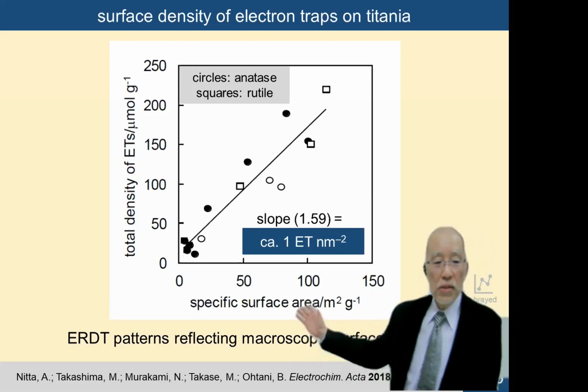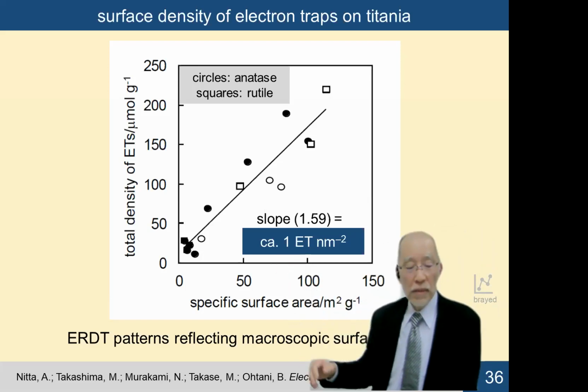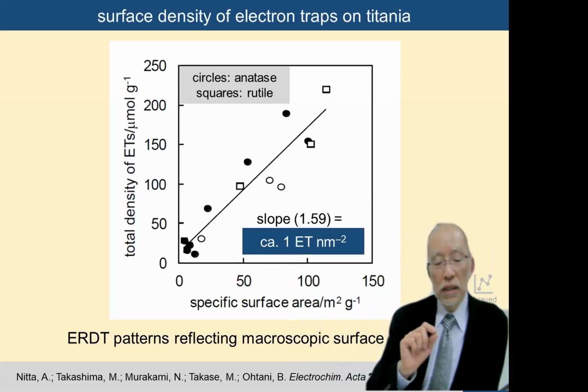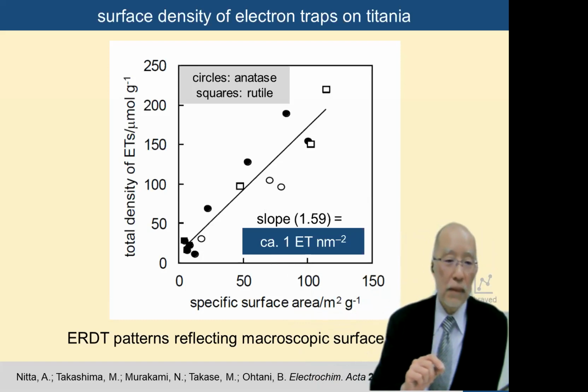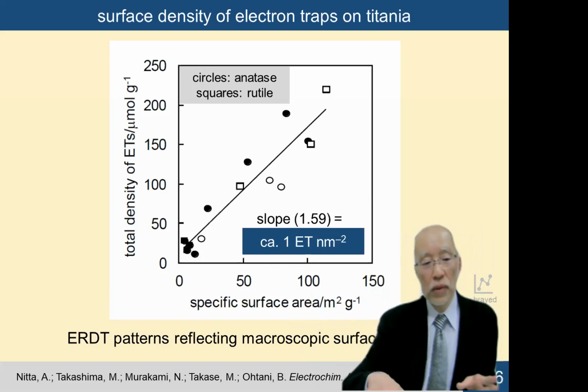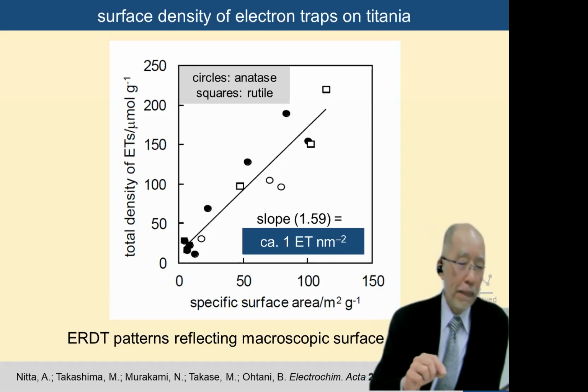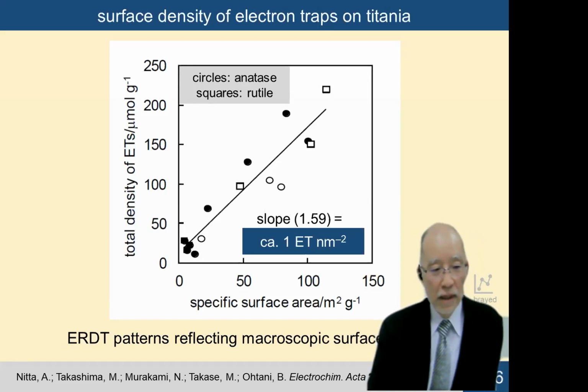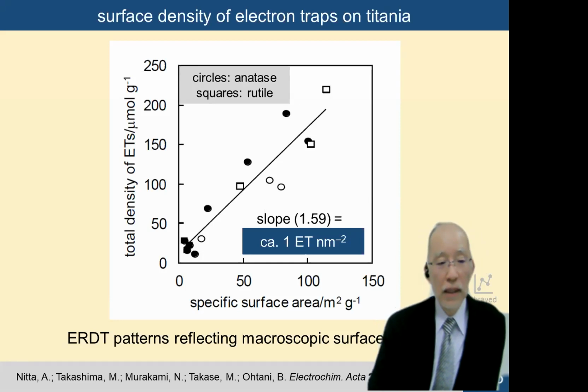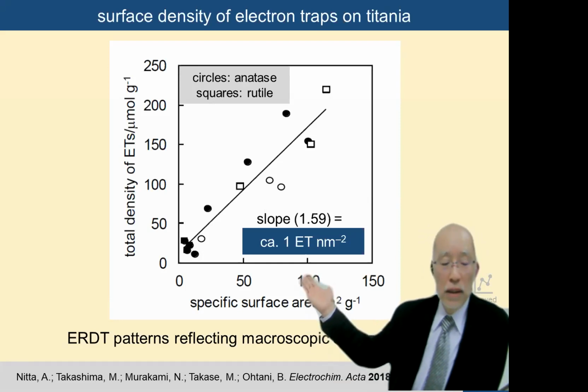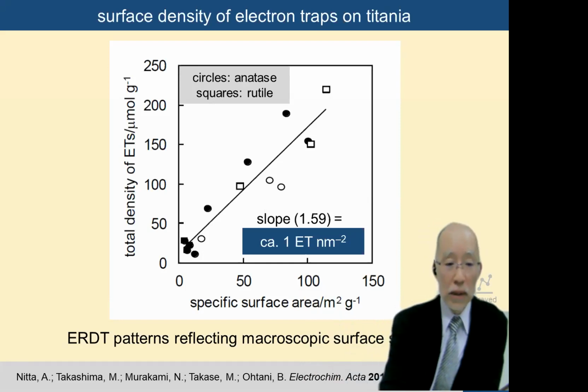And this almost constant density tells us those electron traps are not something like point defects accidentally prepared on the surface. Probably surface reconstruction structures have a certain, specific density of electron traps. So this is our speculation. But the important point is we measure surface electron traps. That means that surface structures are measured by using this technique.